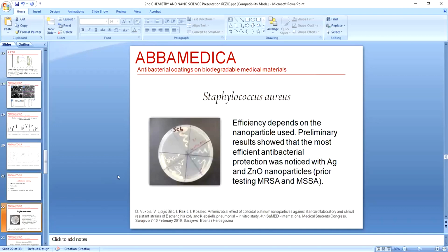So we have been able to have positive effects on Staphylococcus aureus, and we have seen that the efficiency of such effects actually depends on which nanoparticle we use. The first results that we did were preliminary, and those show that the most efficient protection was noticed with silver and zinc nanoparticles. This was done on Staphylococcus aureus. It was a model organism in our laboratory. But afterwards, we really used this